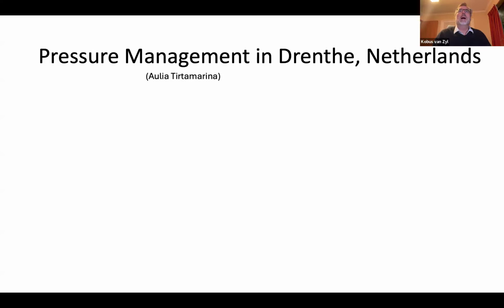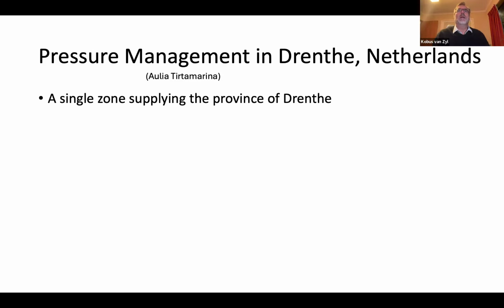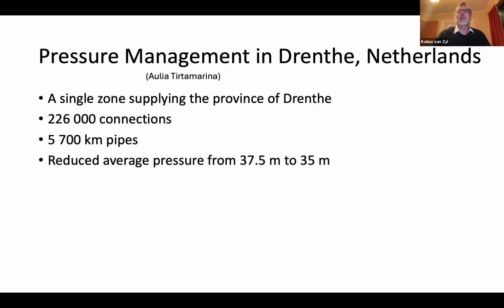And so I got hold of data from the province of Drenthe in the Netherlands. And this is really interesting. It's a single supply zone for the whole of the province because it's so very flat. 226,000 connections, 5,700 kilometers of pipes. And they did this experiment because they wanted to know what's going to happen when they reduce the pressure. So they reduced the pressure from 37.5 meters to 35 meters. So not a big reduction, but on a very big area.